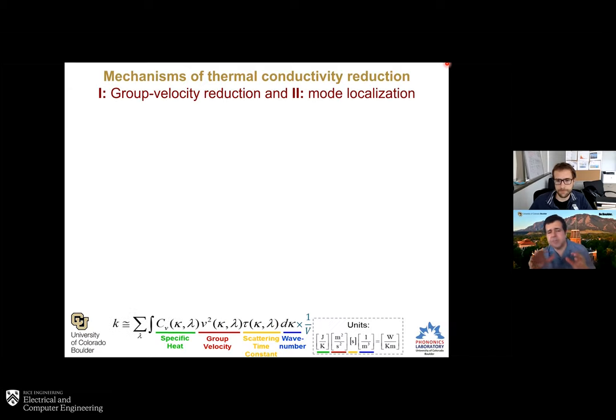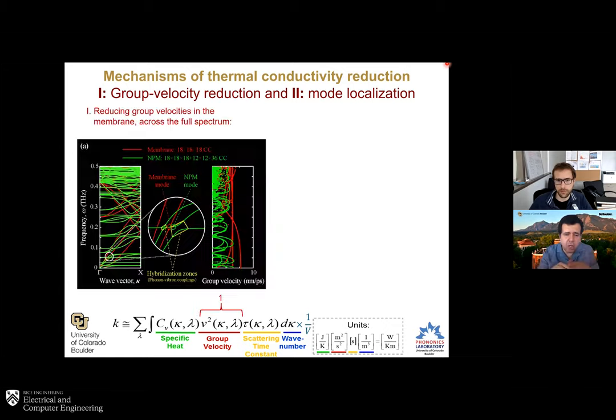Now I'm going to dive a little deeper and show you how this unfolds. This is a picture of the phonon band structure with a bit more detail, showing in green the NPM modes, and the original membrane without pillars in red. In that circle, you can see these hybridization zones where the coupling and the avoided crossing take place. And on the right, which is most interesting, is what happens to the group velocity. You can see that collectively, the group velocities drop significantly across the entire spectrum. We're showing here only 0.5 terahertz, but for silicon, this phenomenon extends up to 17 terahertz. So the group velocities reduce, as you can see there on the bottom.